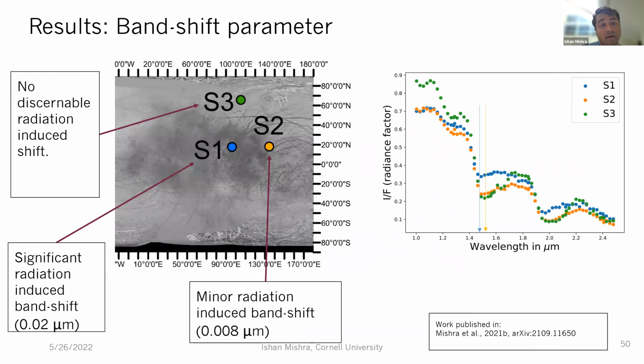All right. Oh, I forgot to mention that one other improvement that we made in analysis compared to previous work is that we included certain physical parameters that were otherwise ignored in previous works. So, for example, remember I mentioned very early on in the talk that particle irradiation actually distorts water ice bands and kind of shifts them as well. And you can clearly see that in this Europa data set, because S1's 1.5 micron band is shifted with respect to S2 and S3.